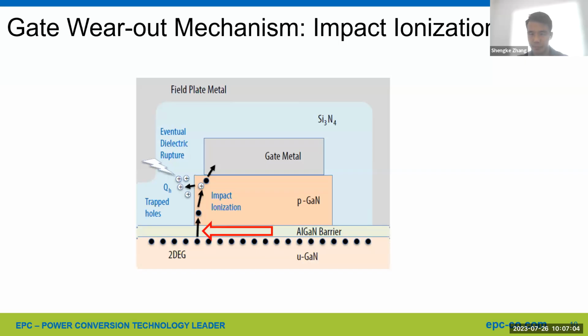In the second step, electrons enter the p-GaN gate and are accelerated rapidly by the electric field, with some gaining sufficient energy to cause impact ionization and generate holes. In the final step, holes try to move away from the gate corner under the influence of the electric field and become trapped in the silicon nitride dielectric layer, leading to a growing positive trapped charge, QH. Once this charge density reaches a critical density, the dielectric ruptures, causing the catastrophic failure mode at the gate corner, as observed in failure analysis.